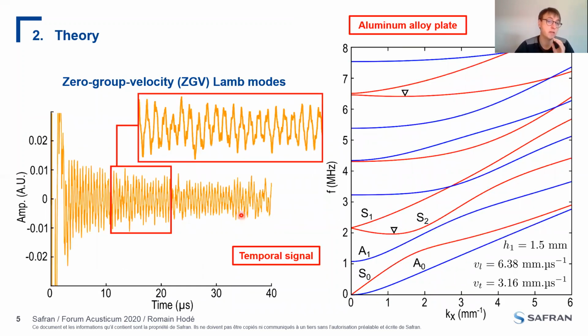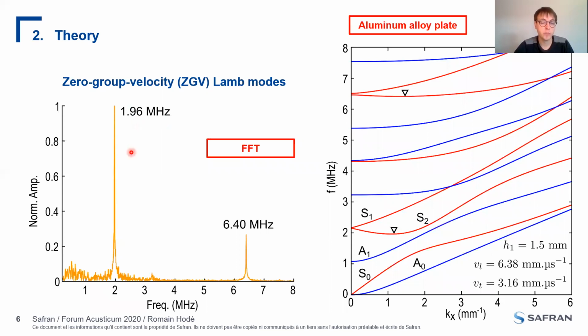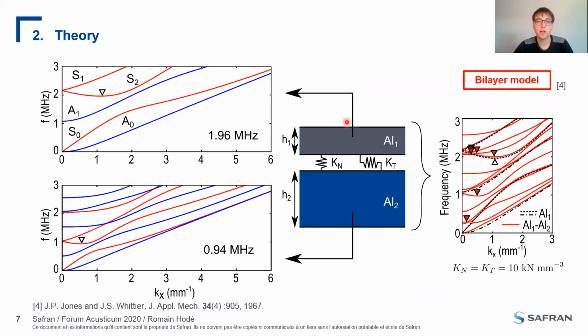So this is the theory, but experimentally, what we can measure is this kind of temporal signal for an aluminum plate. And you can clearly see that we have this frequency here that corresponds to the ZGV resonance frequency around 2 megahertz, corresponding to this point in the dispersion curves that are obtained numerically. And this ZGV resonance around 6 megahertz corresponds to this point in the dispersion curves. And now we can also plot